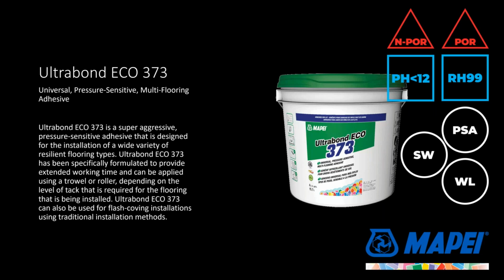Markets changed somewhat, and many of the flooring manufacturers are recommending semi-wet or wet lay applications. And we have verified that Eco 373 can be used in a semi-wet or wet lay application on concrete slabs as long as they're porous. You need to provide porosity at the same RH levels. So 373 can be installed semi-wet or wet as long as the slab is porous at an RH of 99% and still provide functionality. And that will definitely help improve some of the dimensional control of the adhesive. Again, Eco 373 is what I would consider a super PSA. It's very aggressive, very sticky, may have a little bit less modulus than some of the other products we're dealing with. So that's why Eco 399 was developed.